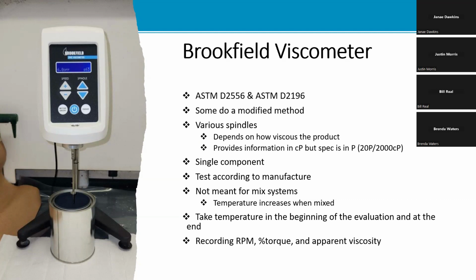So you may do some type of a modified method, but it still corresponds to 2556 or 2196. For this one here, we're looking at a Brookfield viscometer. And for this, you use various spindles. It depends on how viscous the material is. The ASTM or AASHTO you're using will determine which spindle you use. It provides information in centipoise, but the spec, if you read the spec, is actually in poise.